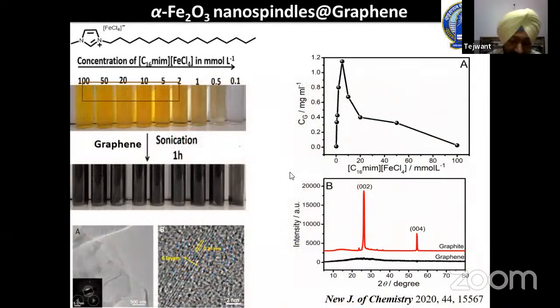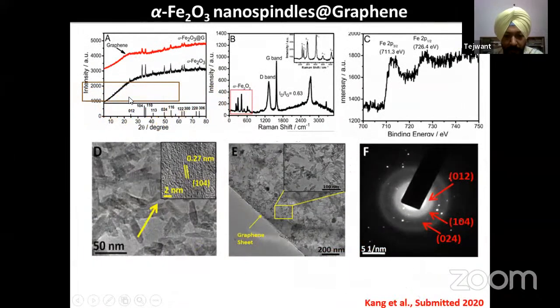This is the general characterization which I have shown you earlier too, like what is the appropriate concentration of surfactant required, and the characterization like what is the quality of graphene which we have exploited using this ionic liquid. Here comes the thing. One can see over there the presence of alpha Fe2O3 nanoparticles on the surface of graphene has been established by XRD as well as Raman spectroscopic measurements.